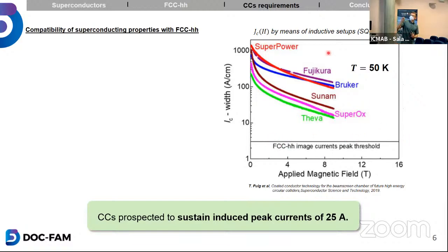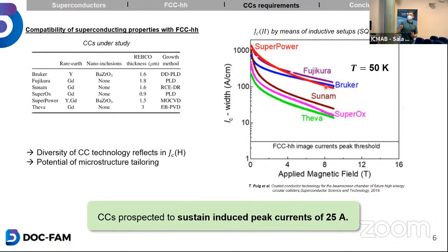Second, although all these coated conductors use REBCO as a superconductor, the field behavior is quite different. So we found a link between the microstructure and the actual performance of the superconductor. Depending on the microstructure of your superconductor, you can have better or worse performance. This is quite exciting because it opens up for material engineers the potential to tailor your superconductor for specific applications.